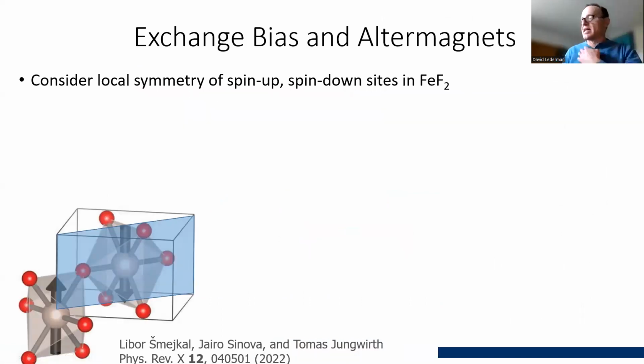This is a very recent idea that has just come out, about what are called altermagnets. In this case, people have been focusing on the band structure of antiferromagnets that have a local symmetry where, for example, an antiferromagnet like this could be iron fluoride, right? You have the spins at the center are spin down, the ones at the corners are spin up. So this could be manganese fluoride or iron fluoride.